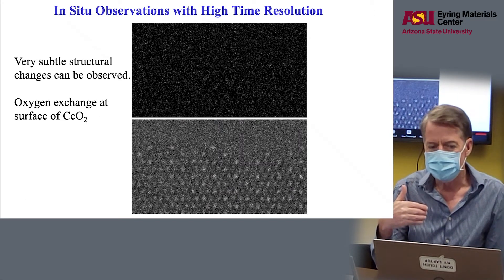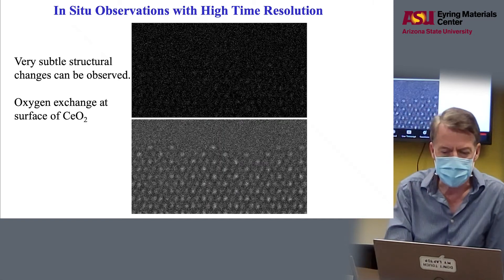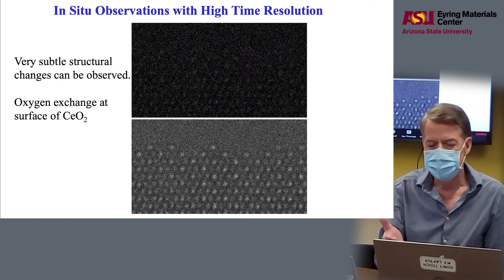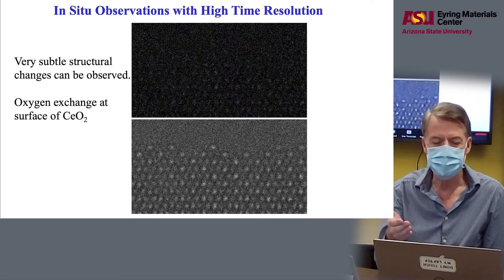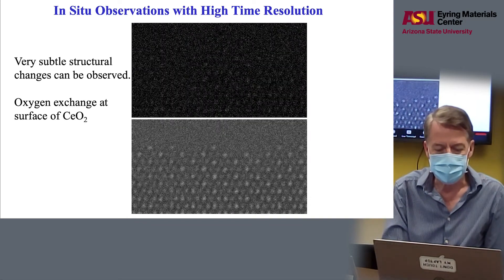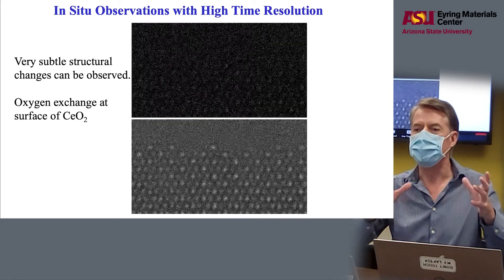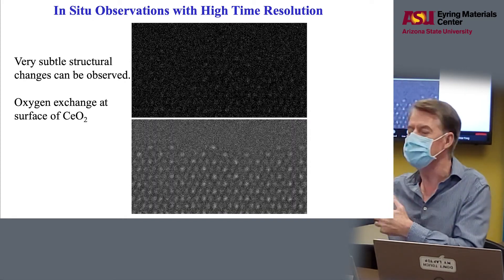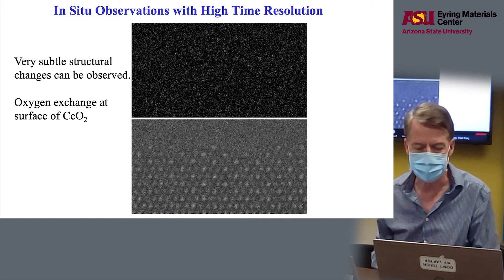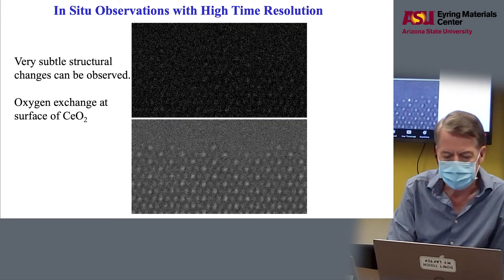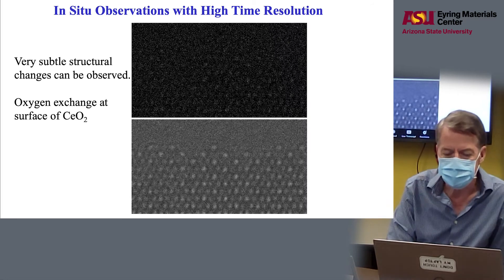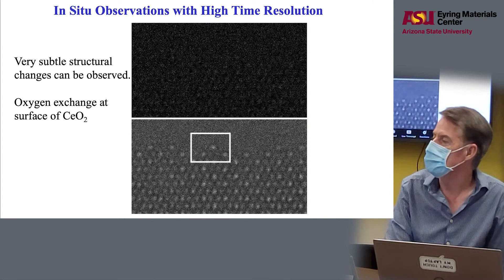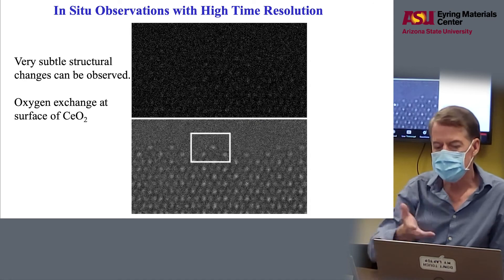You can also do in-situ observations at high time resolution. Running at 75 frames per second, you can decide afterwards whether it's too noisy, whether to frame average, or to sum specific frame ranges — you have complete flexibility in processing the data. This is a cerium oxide surface. We are interested in the oxygens, which show very faint features. Sometimes you see oxygen and sometimes you don't, because oxygen is coming and going in and out of the lattice, and we are able to see that.